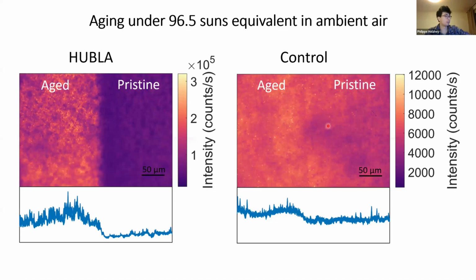And we summarized that in the paper. So here, for the HUBLA film, we aged it under sun. And then after the measurement, I moved the stage a little bit to the side so that in the middle you can see on the left side the aged area. And then you see here the borderline area that's transitioning. So this area was not exposed to any sunlight.